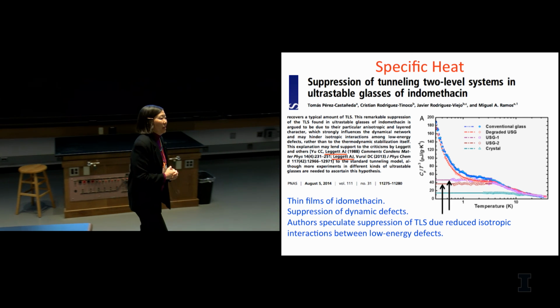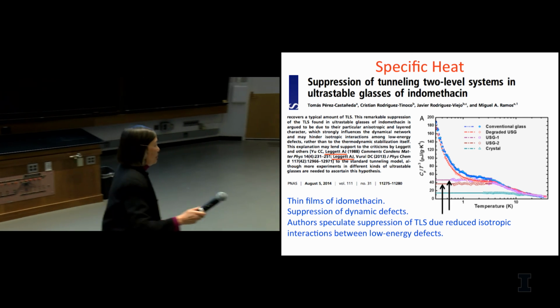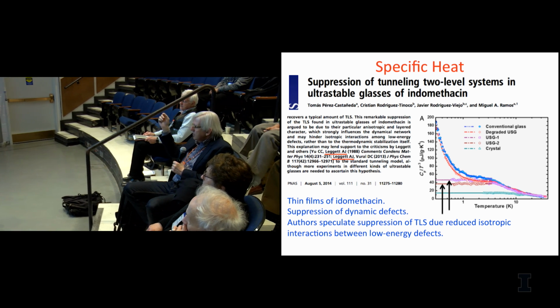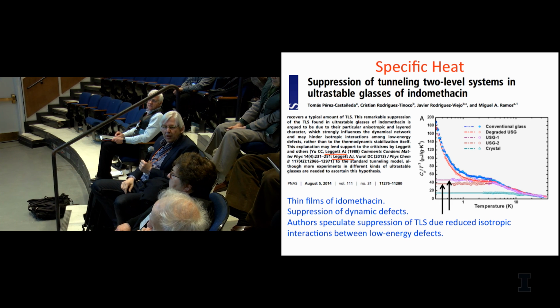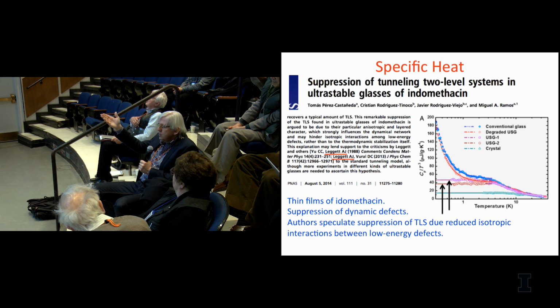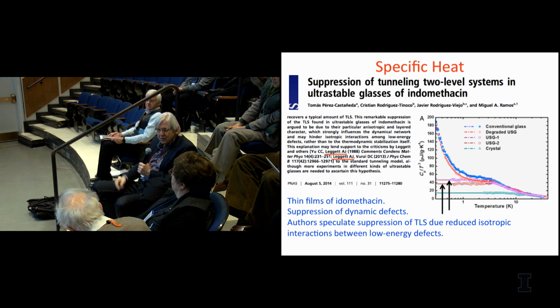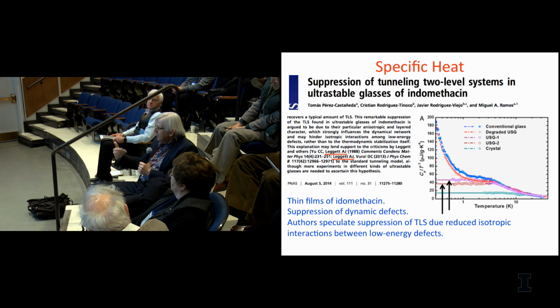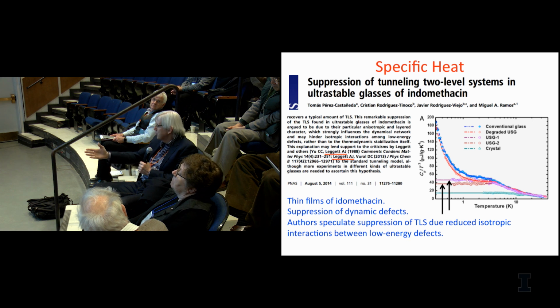Kristen. Just a small comment. When you plot the specific heat, you were pointing out that there's a small deviation from the linear dependence. That has always been a debate, because when you measure specific heat, it changes with temperature, which it shouldn't, of course, as a state property. But in glasses it does, because there are some very slow relaxing systems. And therefore, this was a measurement you showed where I think they took 1,000 seconds per point. So if you wait longer, it gets closer to linear dependence. And if you analyze it in a different way, not just taking the data at this time, so you extrapolate the distribution of times, then you end up with a linear dependence. So I showed the same data, but they were analyzed in a different way. Okay. All right. Interesting. Thank you.